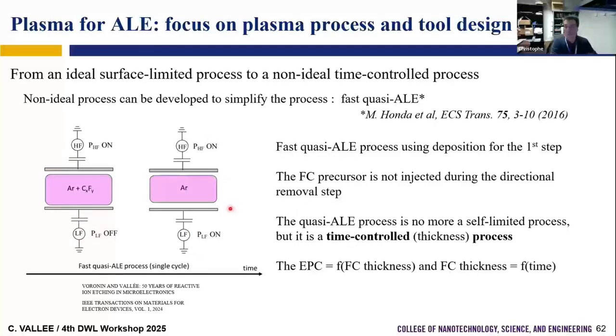Here is an example of what we do, for silicon oxide versus silicon nitride, and I took an example of a process from Tokyo Electron. This is a fast quasi-ALE process from Tokyo Electron. So we do the etching using fluorocarbon for all silicon-based oxide and nitride. Remember, usually by RIE, we use fluorocarbon. So here it is the same. We do an ALE-like process. They call it fast quasi-ALE because it's not ALE, where the plasma source is always on. So we pulse the fluorocarbon when the bias is off. And when the bias is on, we have no more fluorocarbon. So here we do the chemistry, and here we do the removal. And here we don't do any surface fluorination. We deposit a very thin fluorocarbon layer at the surface.